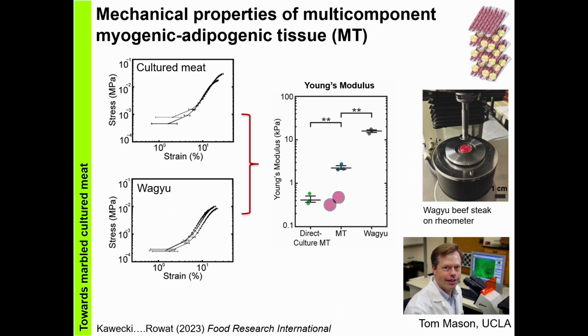And just to summarize here, you can see the Young's modulus that we've quantified. And you see that our microtissues, this is the multi-component microtissue MT here, has a lower Young's modulus than the Wagyu. But we were also interested to see that the multi-component tissue that we take directly out of culture has a lower Young's modulus as well. But we were able to tune and achieve an order of magnitude increase in this Young's modulus simply by dehydrating slightly the sample, just by wicking away the moisture overnight.